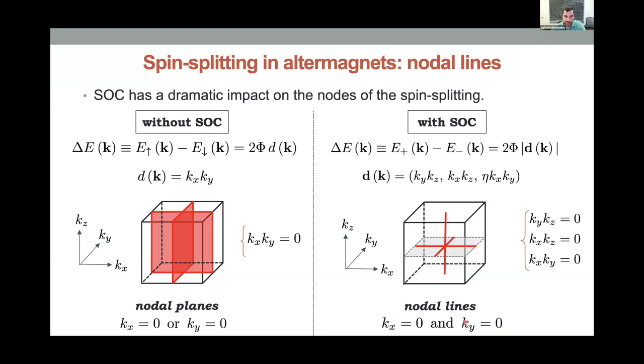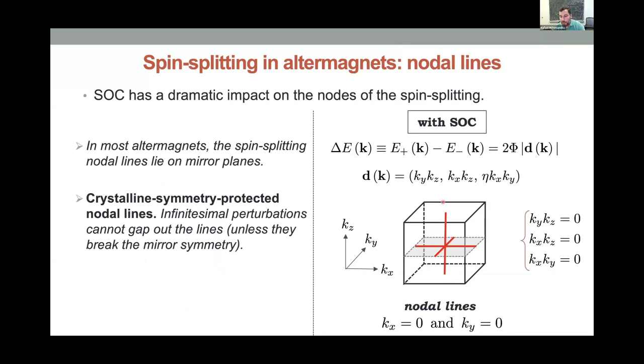But what is interesting and important to notice, and this is not particular to this example, is that these nodal lines are actually pinned to high symmetry directions by the mirror symmetries of the crystal, okay? And in this regard, if you do an analysis of nodal lines with respect to just the global symmetry properties, they are topologically trivial. However, they are still protected by the crystalline symmetries. Okay, so these are crystalline protected nodal lines. And in this case that I'm showing you, there are two mirror planes protecting them. That's why they are pinned to be along this direction. Okay. Now, you may say, okay, well, sure, you have nodal lines that are symmetry protected, but why should I care? Well, you should care because it will matter when I perturb my system.